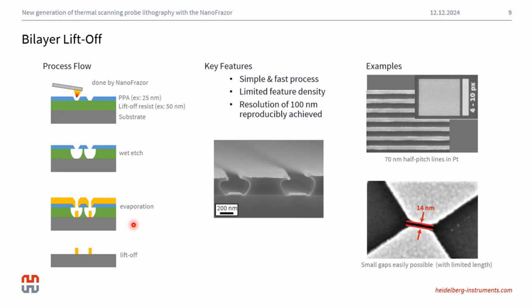Then an evaporation, either to metallize the structures or any other material deposition as well. Then we perform a lift-off step. In the most common of cases, this is done simply with acetone or DMSO, and we recover our final features. Some examples of the bilayer lift-off are shown here, and I'll show more of this also during the next slides in my talk. The limitation of this method is, as you can imagine, the resolution due to the isotropic nature of the wet etch pattern transfer method.